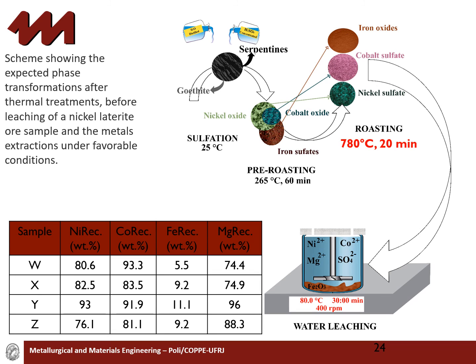The scheme exhibited in this figure exemplifies the mineral phase change involving nickel, cobalt, and iron compounds for the sulfation roasting step before leaching. The main idea is to obtain nickel and valuable metals such as cobalt in the form of sulfate, while iron should remain in the form of oxide to reduce the acid consumption. The best results were obtained by the sulfation at room temperature, followed by pre-roasting at 265 degrees for 60 minutes, roasting at 780 degrees Celsius for 20 minutes, followed by cooling until room temperature and leaching with water.